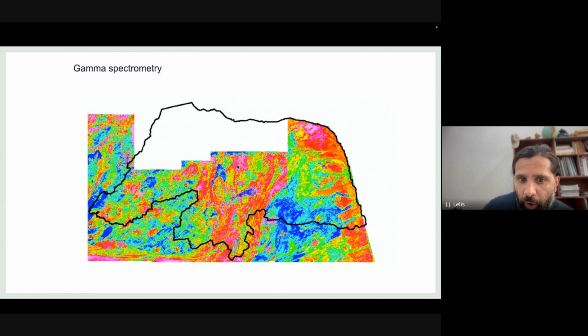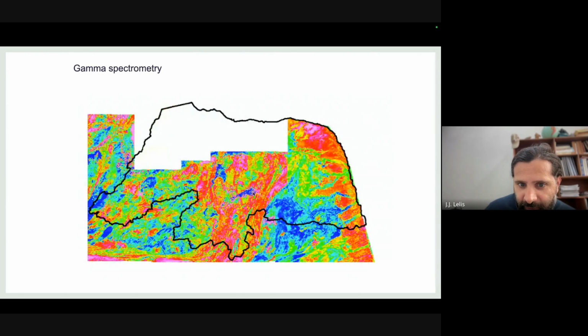So when you have these blue colors, you have more thorium. When you have this pink and red colors, you have more potassium, and when you have this green color, you have an average content of potassium and an average content of uranium, okay? So you can see very, very easily that these differences of colors are related to the differences of parent material. Just check it again. For example, in this specific zone, we have this yellow rock, and here, you can see it here. Okay, the shape is not 100% equal because each one has one specific scale and a minimal resolution, but you can see both.